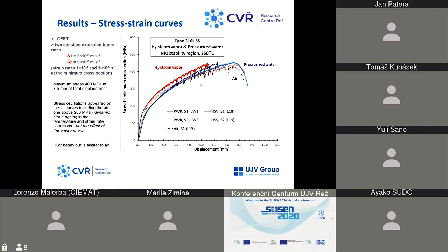And this is not the effect of the environment, but the dynamic strain aging under these temperature and strain rate conditions. So what we can see here is that the hydrogenated steam vapor behavior is similar to the air and basically similar to the pressurized water.